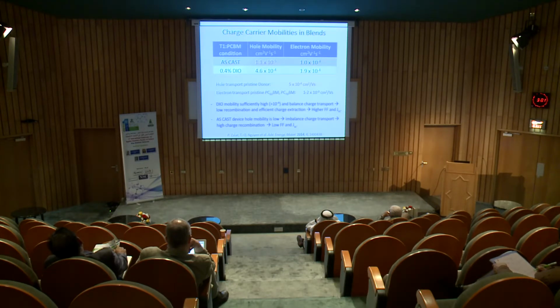So what is the implication of that? If you have imbalanced charge transport in your device, it means that one type of carrier is sitting around in the device longer, so you increase the probability for them to recombine. And when you have stronger charge recombination, you can have a lower fill factor and therefore lower short circuit current and lower device performance. So now let us look at the device processed with 0.4% DIO.